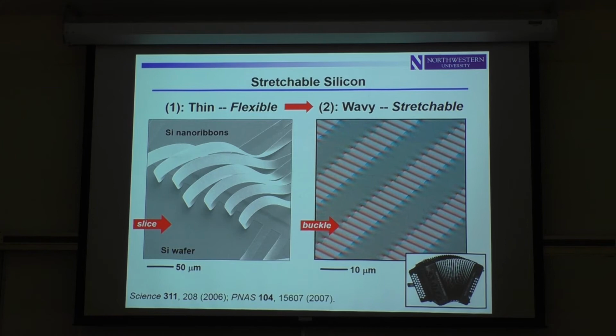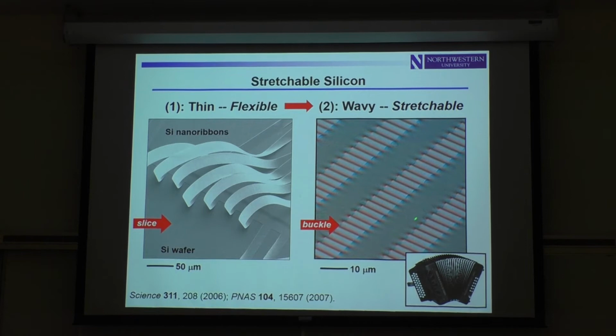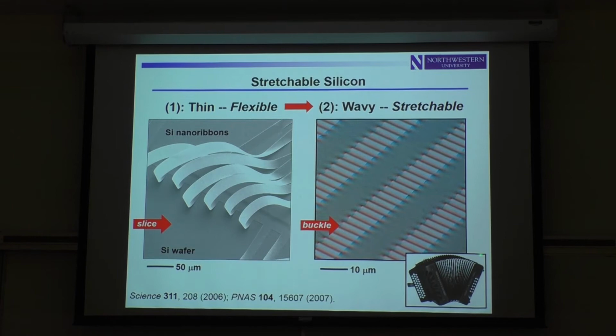And I won't get into the details. It's pretty simple conceptually. You take these very thin sheets or ribbons of silicon, you bond them to an underlying silicone substrate, as I was suggesting in the previous slide, but you bond them not in a flat geometry. You bond them in a wavy, buckled sort of shape. And by doing that, you essentially create a hard, soft, deterministic composite structure that provides the electronic functionality, the hard brittle component, and the elastic mechanics associated with the underlying substrate, with an overall combined mechanics that's very conceptually similar to that of an accordion bellow.